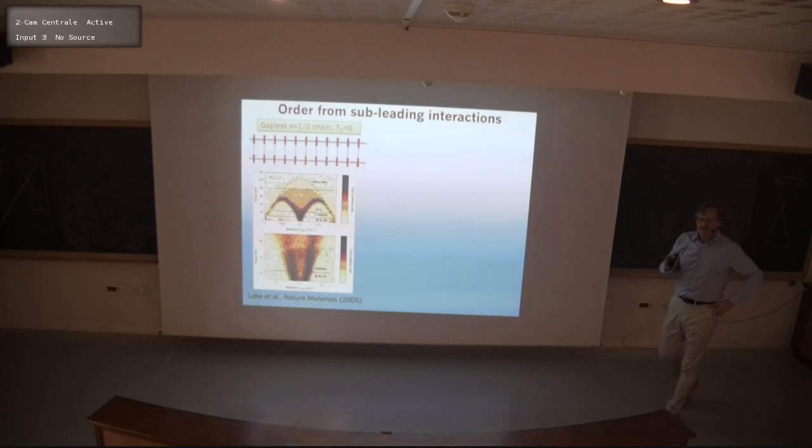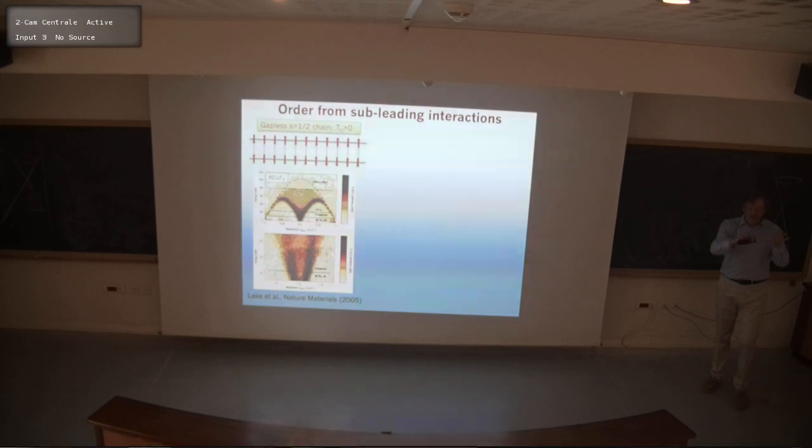Okay, I would like to say a little bit about the connection to materials, because I think most of the talks and many of you are aspiring theorists, but actually materials tend to be quite complex, a lot of degrees of freedom that are not central to the physics we're trying to do, but they impose themselves and really impact the experiments. And in the case of one-dimensional magnetism, there are always interactions between the spin chains. If something is not forbidden, it's mandatory. So since we're not forbidden from having interactions, there will be interactions between the chains.